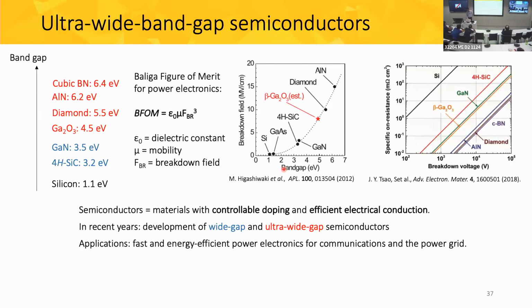So take silicon, for example. If you want to make silicon operate at 1,000 volts, you can do it. You can make silicon microchips operate at 1,000 volts. The problem is you have to make them big, and that means that you have to make them very resistive. They act like a huge resistor, and they're slow. So we don't want silicon for power electronics. In fact, this is one of the things that silicon does not do well, no matter the cost.